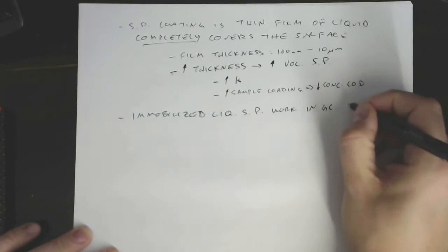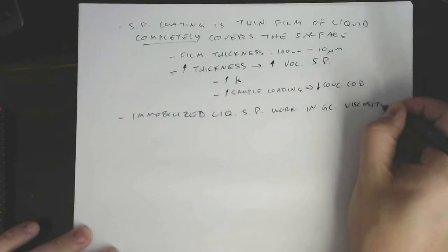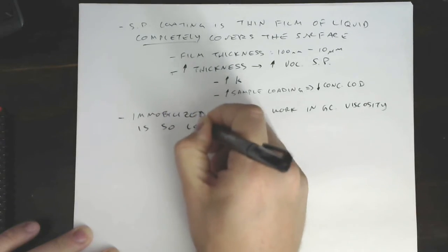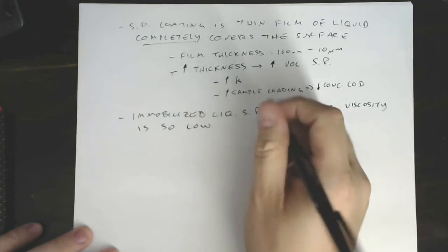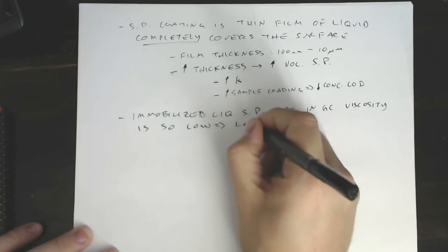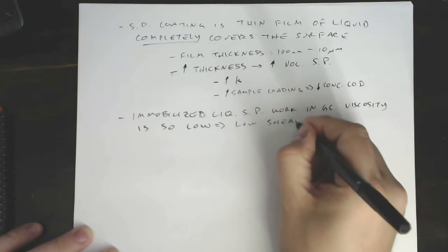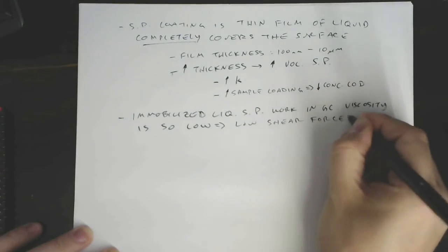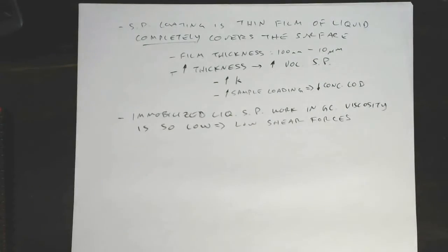These immobilized liquid stationary phases work in GC because the viscosity is so low in gases. Low viscosity means low shear forces, that is, low forces acting on that liquid film as the mobile phase runs past the liquid film. So if we had higher viscosity, like in a liquid, we would essentially wash that liquid film off. This is the same reason why every time the wind blows, it doesn't empty out a pond or a lake or a puddle, because the shear force of the gas going over the surface of a liquid is not always enough to rinse off that liquid completely.